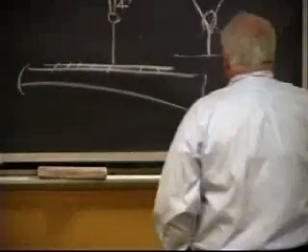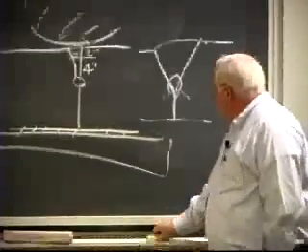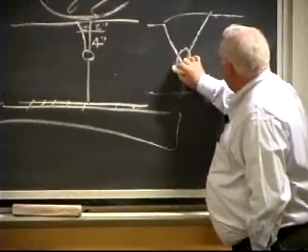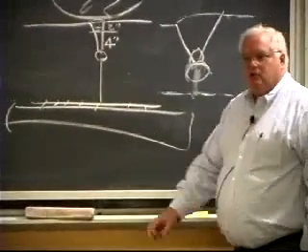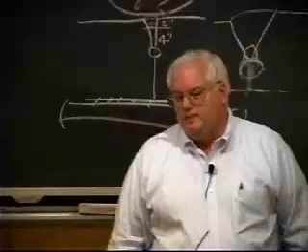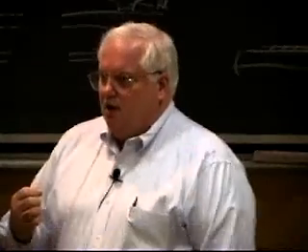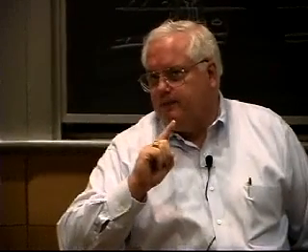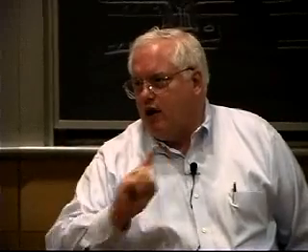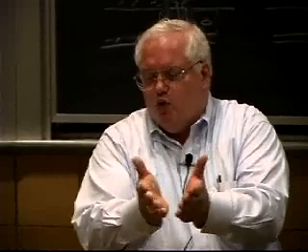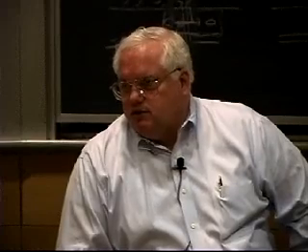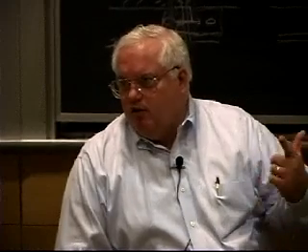What you're doing is you're burning out the defect, and on the back side you end up with a nice rounded groove. Now when you put the weld in there, without any sharp corners, you get good fusion all the way around the root. But if I want to make a defect-free, full penetration joint from both sides, because it's a thick piece of steel, I'm going to have to either grind or air arc gouge out the defects at the root, because when I originally designed that thing, I have kind of a sharp corner, and the metal doesn't get down there and fuse like it should. So the standard process is what we call back gouging, grinding or air arc gouging.